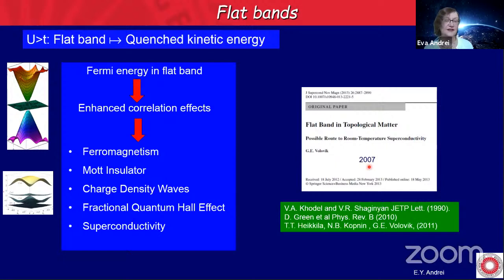So that was a huge incentive for people to start looking for flat bands and to start trying to manipulate the Fermi energy there. Of course, you cannot do that in a bulk material because you can't change the Fermi energy. In a bulk material, you just get what you can get. But in two-dimensional materials, you can actually manipulate both the band structure and the position of the Fermi energy.